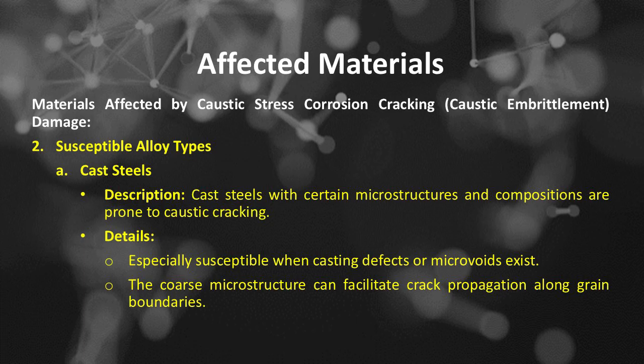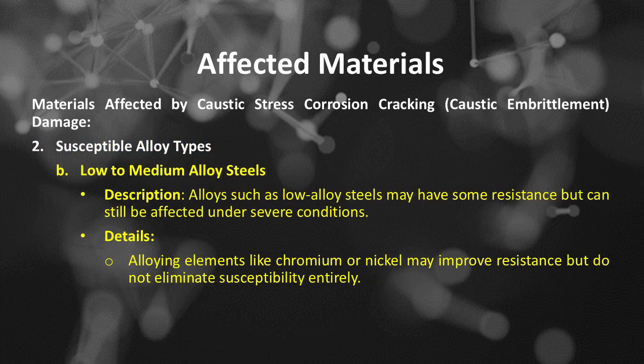Details of cast steels. Material affected by CSCC, especially susceptible when casting defects or microvoids exist. The coarse microstructure can facilitate crack propagation along grain boundaries. Number B, low to medium alloy steels. Alloys such as low alloy steels may have some resistance but can still be affected under severe conditions. Details of low to medium alloy steels. Material affected by CSCC, alloying elements like chromium or nickel may improve resistance but do not eliminate susceptibility entirely.